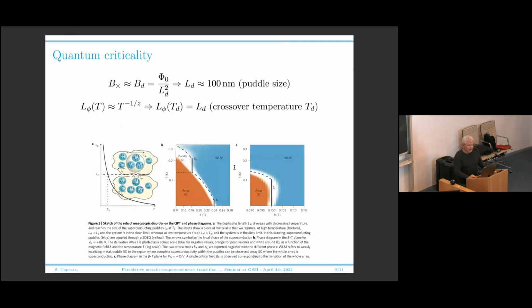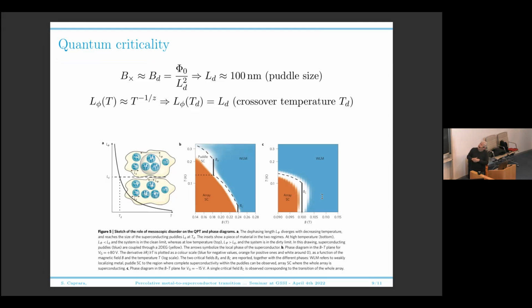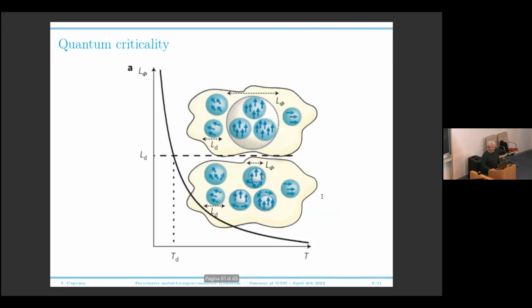This is the interpretation. At large gating, where you are deep inside the metallic state, you have, as a function of the field, the possibility to have puddle superconductivity and then array superconductivity. Whereas when you are deep inside the depleted region, you have only one superconductivity, the array superconductivity. Why is this so?